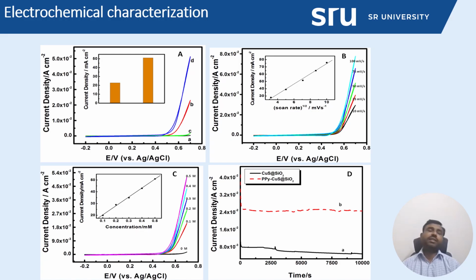Whereas in the polypyrrole coated case, it behaves as a protective layer, so the copper sulfide is not affected by the oxidation product. Hence it continuously delivers full catalytic performance up to long-term stability. Further, the copper sulfide has good conductivity. Hence it allows a larger number of methanol molecules to interact with the copper sulfide active sites.